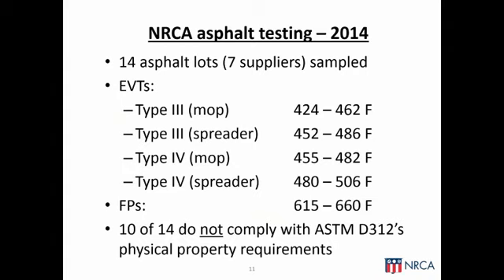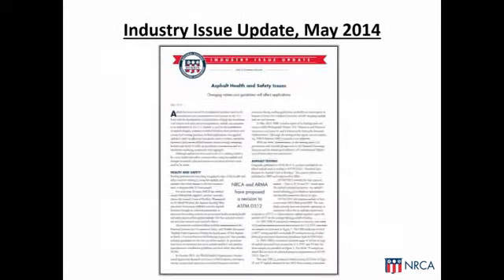Because what we do have to acknowledge in the industry is that there is some temperature drop in asphalt between the kettle or tanker and the point of application on the roof. Flash point out in the field on the roof is a kettle temperature or tanker temperature, and EVT is a temperature at the point of application. There is a temperature drop in between. And when we have EVTs and flash points overlapping or getting very close to each other, that becomes an asphalt that is, for all practical purposes, not feasibly installable in the field.